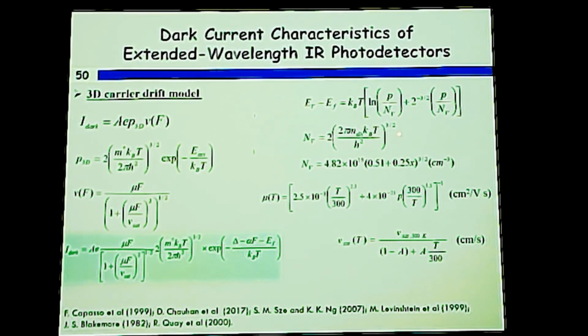density of states, which is given by this, and also there is an empirical relation for this term. And also for mobility, there is an empirical relation that depends on the doping density and the temperature. And saturation velocity also has an empirical relation, where A is not the area; it's just a constant. Okay. And for gallium arsenide, the reported value is around 0.6 or so.